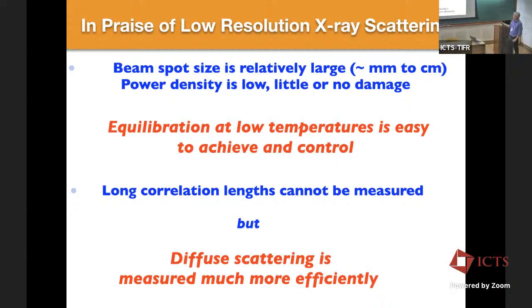So our beam spot size compared to most X-ray diffraction is relatively large, and what that means is that the power that's delivered to the sample is relatively small. It's about a factor of 10,000 lower than the equivalent experiment on even a not particularly up-to-date synchrotron. And so there's two things. One is that there's essentially no beam heating. With the synchrotron-based X-ray scattering experiment, there's a lot of beam heating. In fact, it essentially precludes measurements with X-ray scattering below about 10 Kelvin.